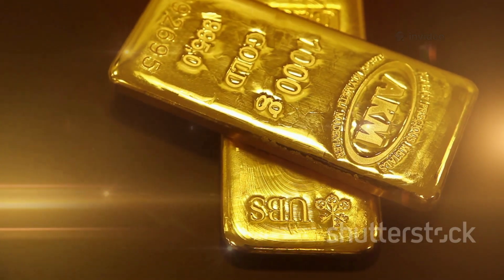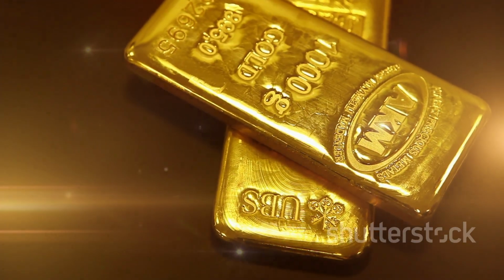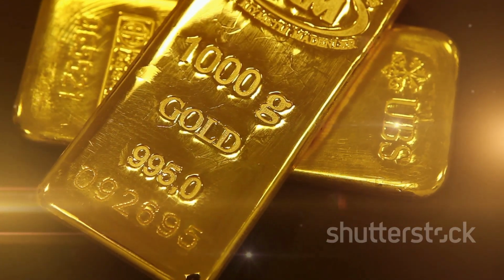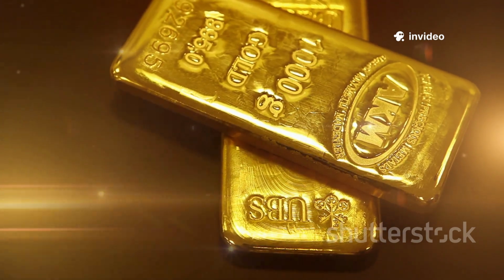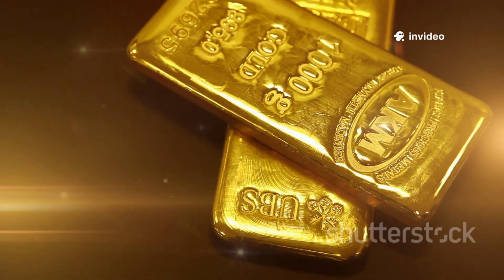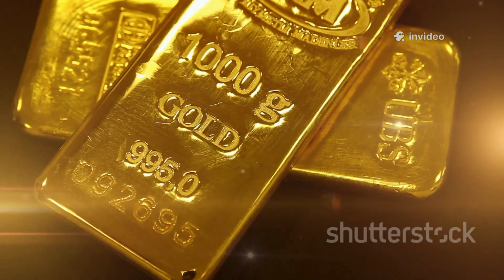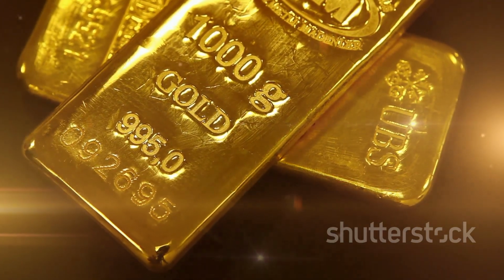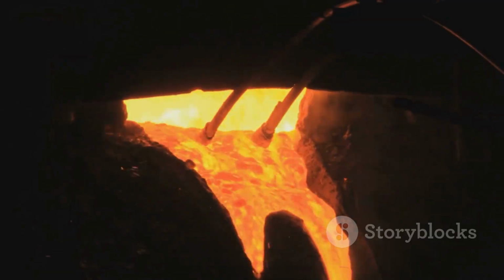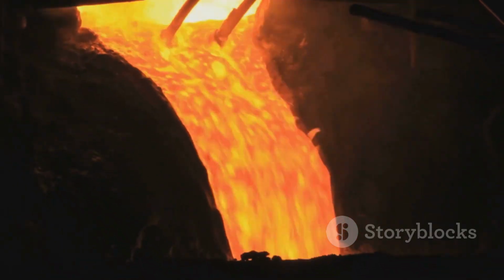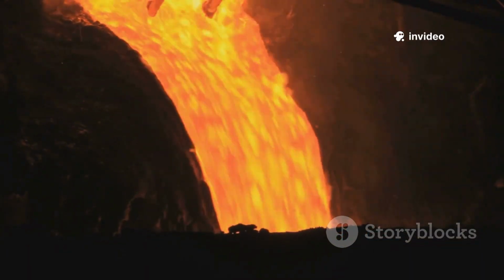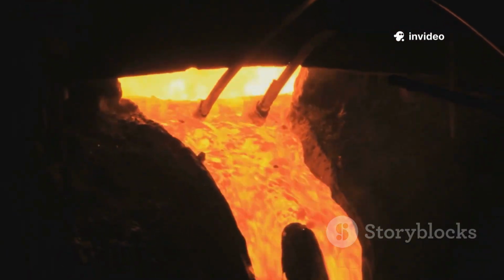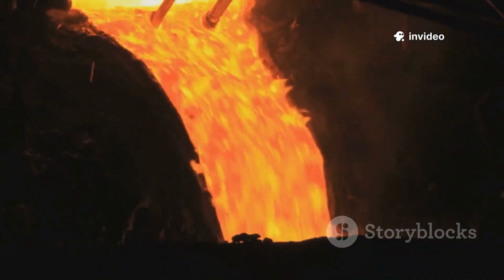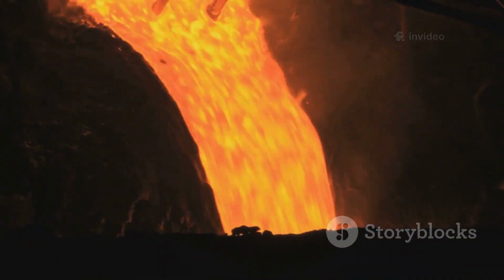When an electric current is applied, the gold from the anode dissolves, travels through the acid solution, and plates, atom by atom, onto the pure gold cathode. Any remaining impurities fall to the bottom as a slime. This slow, careful process creates gold of exceptional purity. After the refining process, we finally have it. Gold of at least 99.99% purity. It exists as a gleaming molten liquid, ready to be shaped into its final iconic form.